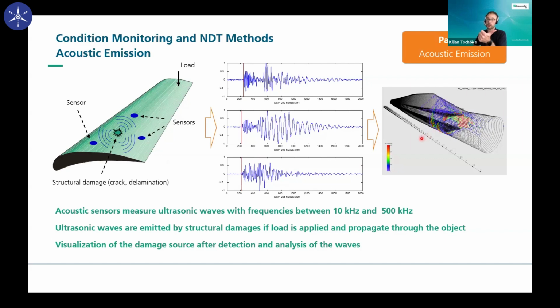One can localize the position of the damage by analyzing the signals, for example, in frequency or amplitude or duration. One can also get information about the type of damage. So especially in composites, different damage like delaminations or debonding, they have different features in frequency domain and in the amplitude. So to say, different damage, they make different noises, and this can be identified by your system.